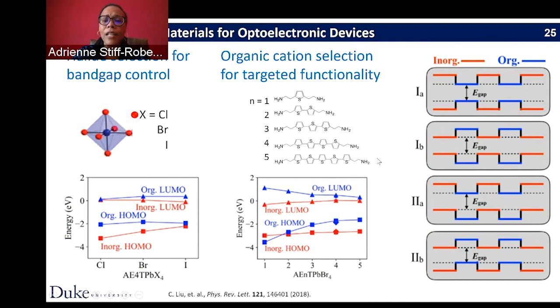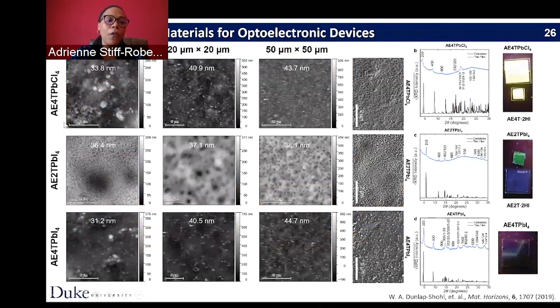And so this is where the MAPLE was really able to contribute to this because we were able to grow different combinations of these large molecules and the metal halides, deposit thin films of these materials. So here we're looking at AFM images and then SEM images of these materials, as well as the X-ray diffraction spectra that match what you would expect for a bulk crystal.